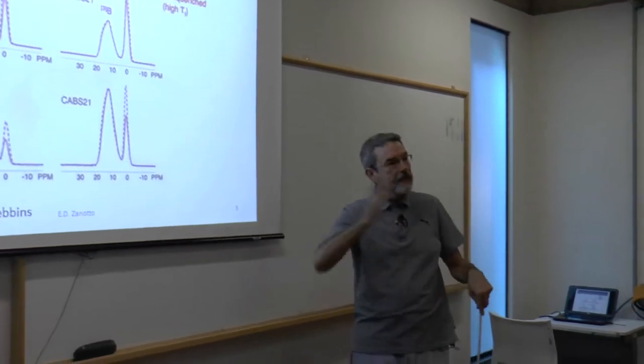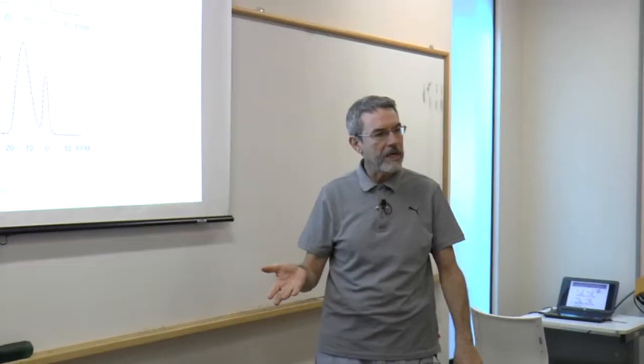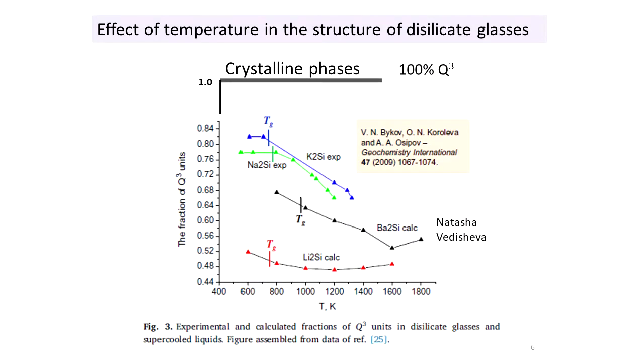Not completely different, because it's the same glass, but these kinds of plots, and there are many others in the literature, show that the cooling rate affects the finest details of the glass structure. So it's not only a schematic plot that we draw. The actual structure is different depending on the cooling rate, or on the thermal history of the material.